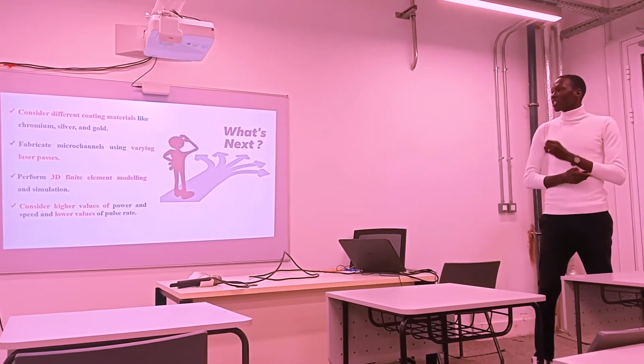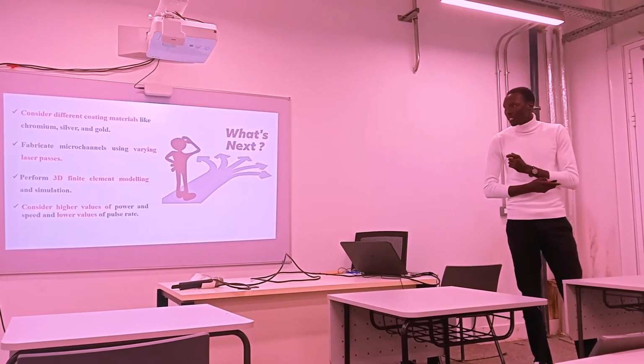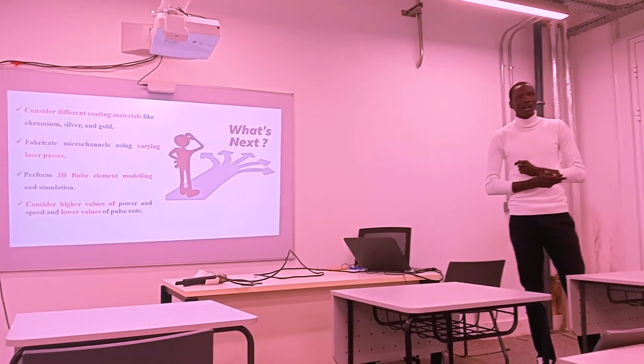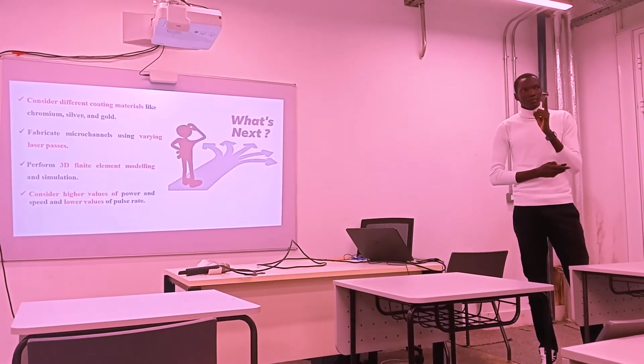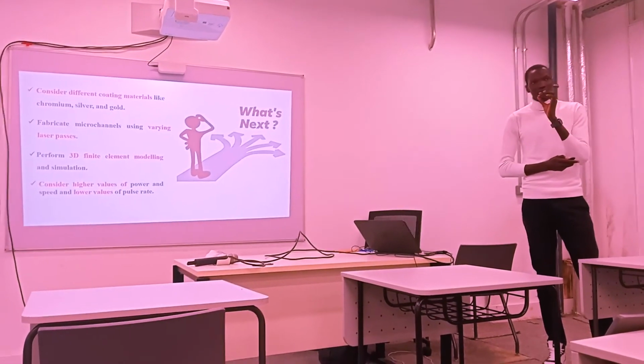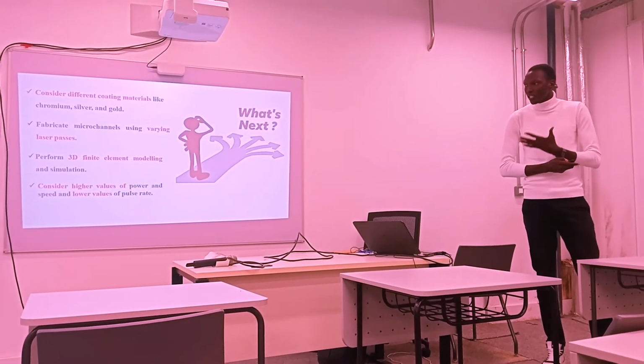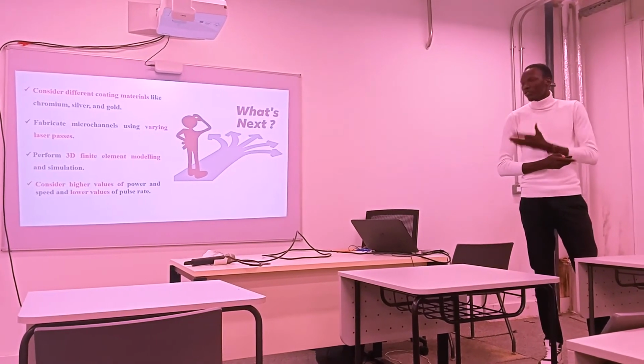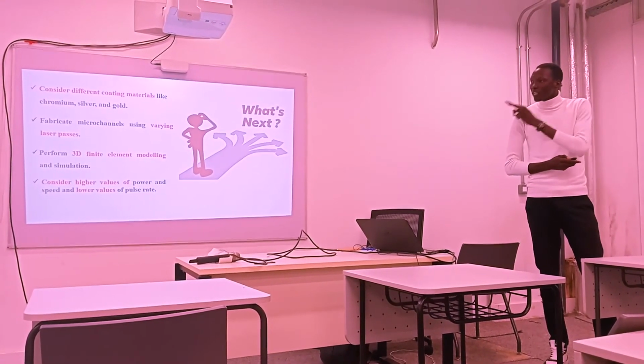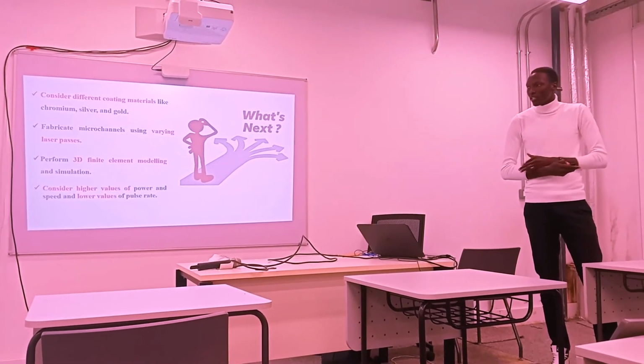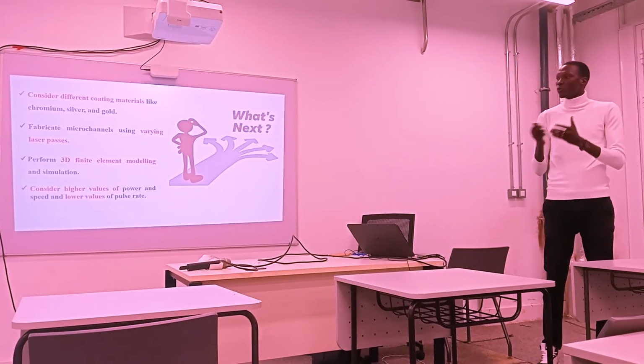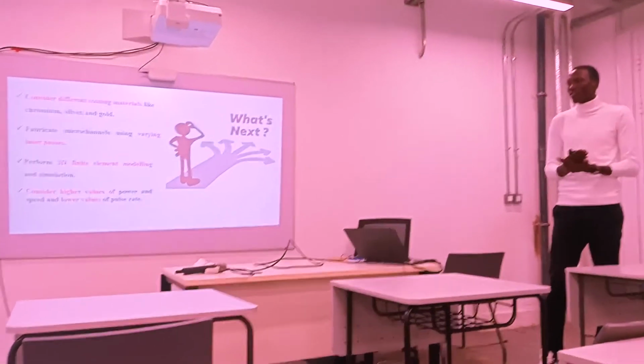Now, future studies should also consider higher values of power and speed and lower values of pulse rate. Our maximum value of power was 7.5 and maximum speed was 30 millimeters per second. So, future studies should consider higher values of power and lower values of pulse rate. We were fixing pulse rate for part 1 at 1,000. And for part 2, we varied 800 and 1,000 pulses per inch.